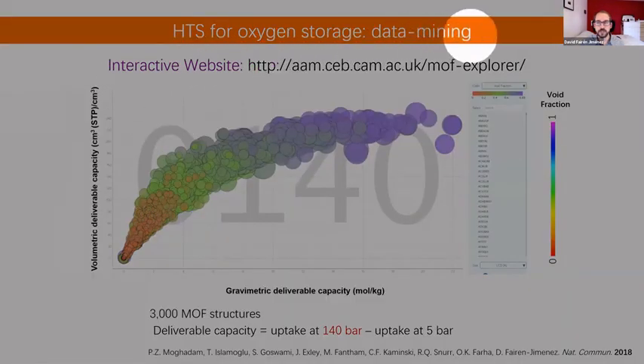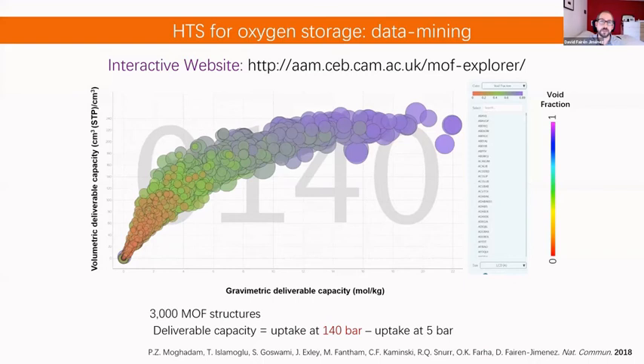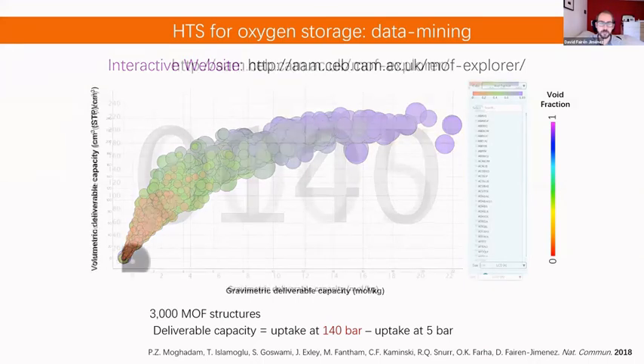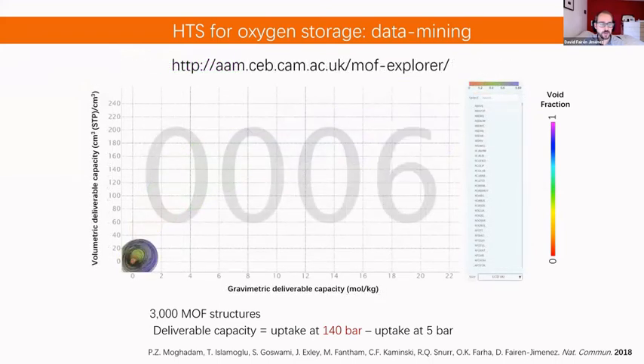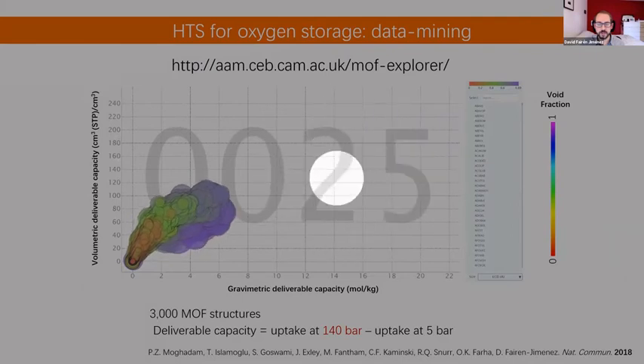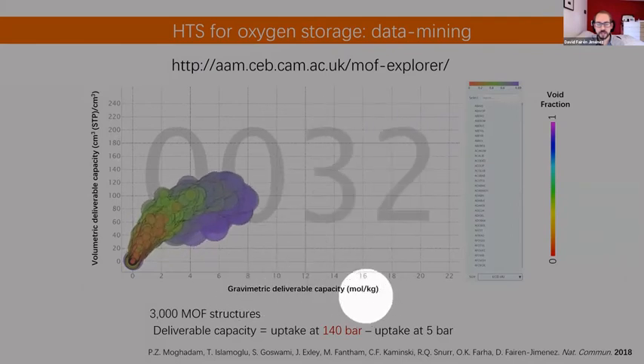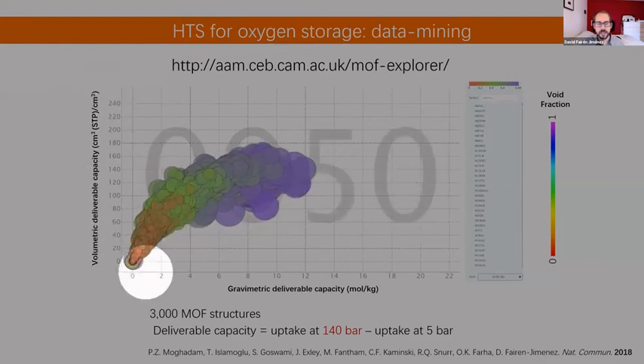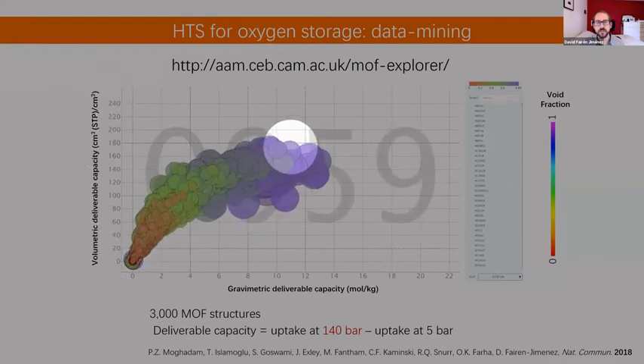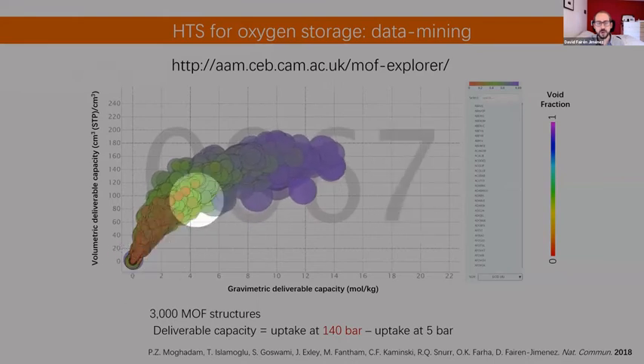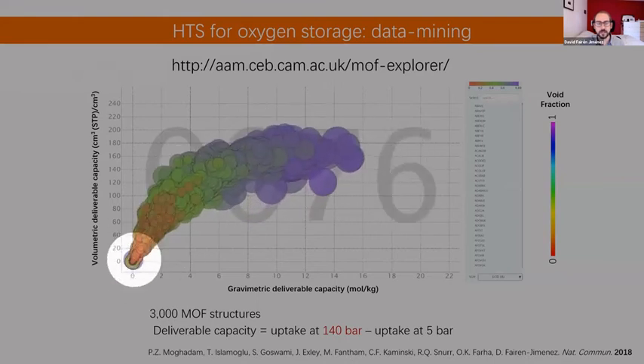This is something that is stored at the academic group, but as I said, this is something that we have developed together with IMMATERIAL. We have spun this out into IMMATERIAL. What you are going to see here is the pressure for the different simulations. This is the amount of gas stored per unit of mass, and this is the amount of gas stored per unit of volume. Every point you see here is one different metal organic framework. So you can see how all the different metal organic frameworks' capacities evolve when we increase the pressure.